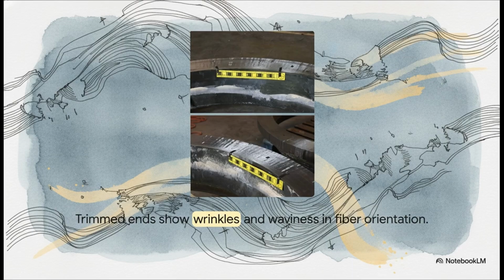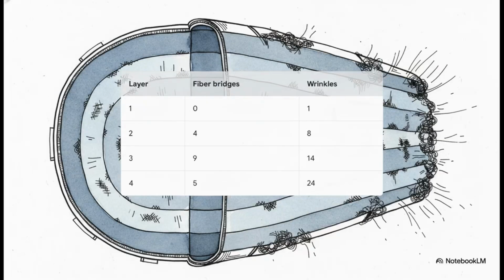During manufacturing, OceanGate actually had to grind down up to 12 layers of these wrinkled carbon fibers just to keep the hull's shape flush enough to apply the very next layer. Every single time they ground down a wrinkle, they were permanently snapping continuous carbon fibers, instantly degrading the hull's structural strength. Now check out this specific NTSB data table.